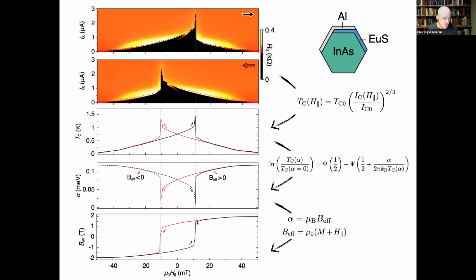So what that tells you is that if this analysis goes through, this mean field analysis and this analysis in terms of associating the pair breaking term with the Zeeman field, the system feels as if it's in about a 1 Tesla to 2 Tesla magnetic field, except right here, where it crosses through zero when the field flips its direction. So in particular, if you ramp up the magnetic field and ramp back down to zero magnetic field, the system feels like it's in a Tesla.